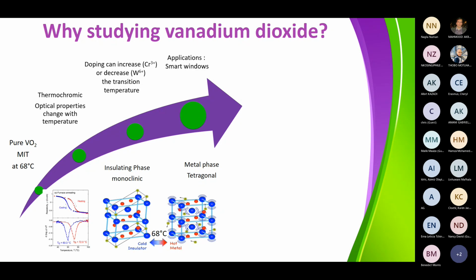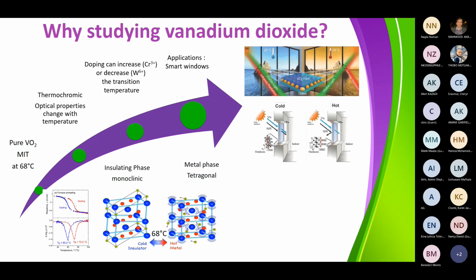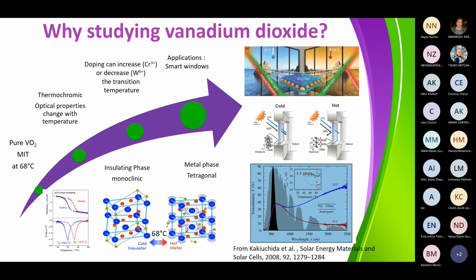Of course, the applications of these materials are smart windows. So how does it work? If you are in the insulating phase, you can transmit the sunlight through windows on which you have put a vanadium dioxide film, and you can transmit the infrared radiation, while if you are in the metallic phase, because it's a metal, it's going to reflect the infrared radiation. This is very interesting in many countries where when it's very hot, you don't want the light, especially the infrared light, to go through the windows. It's also shown here on this graph. You can see that if you look at the transmittance of, here it is.